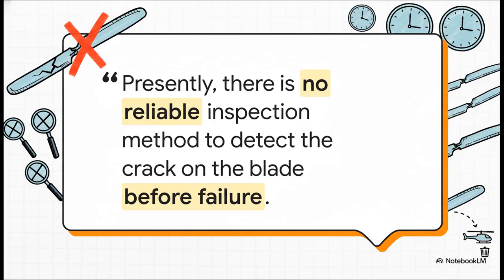And this quote, right from the directive itself, is the final piece of our puzzle. It is a stunning admission. The regulators are basically saying, we can't find the crack, so the only way to be safe is to get rid of the blade long before the crack has time to grow. They couldn't fix the problem, so they had to remove the risk entirely. A hugely expensive decision, but it shows you the challenge of dealing with these invisible, hidden defects.